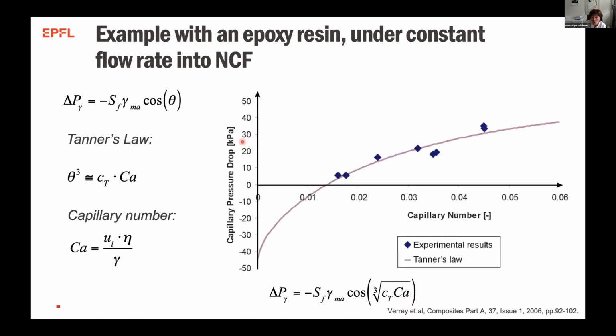You see that the capillary pressure drop we measured, in our case, we had a quite high capillary number. It was with the epoxy resins into NCF, but we see that it increases as I increase the velocity of the resin. I have this capillary pressure drop, which remains quite small, which has an influence, but it increases with the capillary number, sorry. And then we extrapolated that this is the static contact angle that we measured. So if you just look at the static contact angle, your values are completely wrong because you think it will wet, but in fact, it's actually non-wetting, and you have a positive capillary pressure.